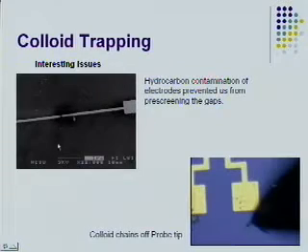And there's some other interesting issues. I don't know if you can see this, but we were pre-screening the electrodes under the SEM before we would run these experiments, but it was depositing a contamination film on it. So therefore, we weren't able to pre-screen these electrodes anymore because we couldn't get accurate IV characteristics if we contaminated the surface, and it also could change our trapping conditions and have an effect.